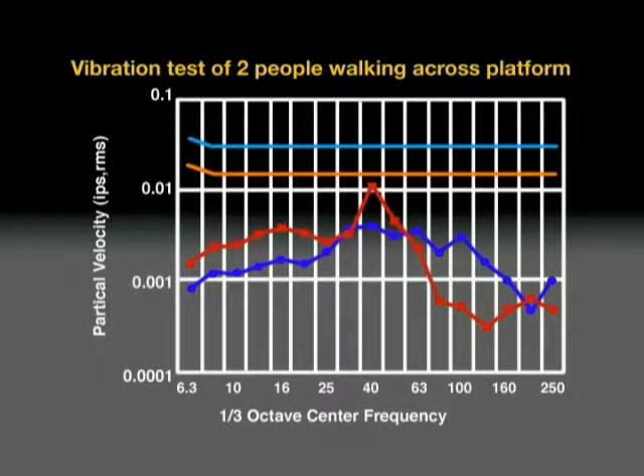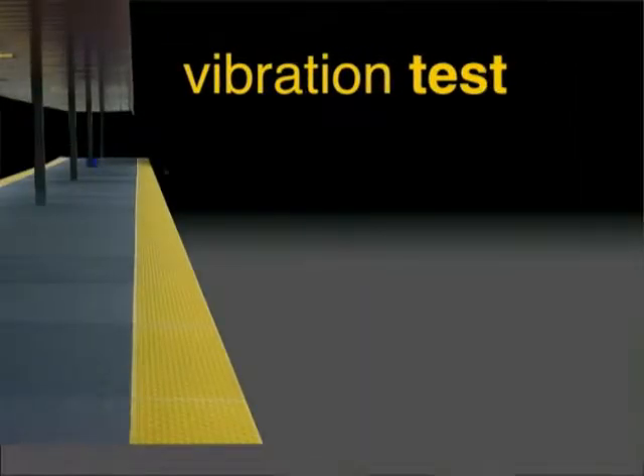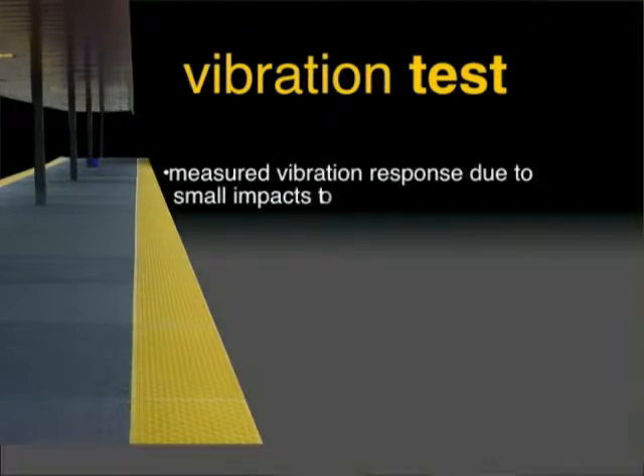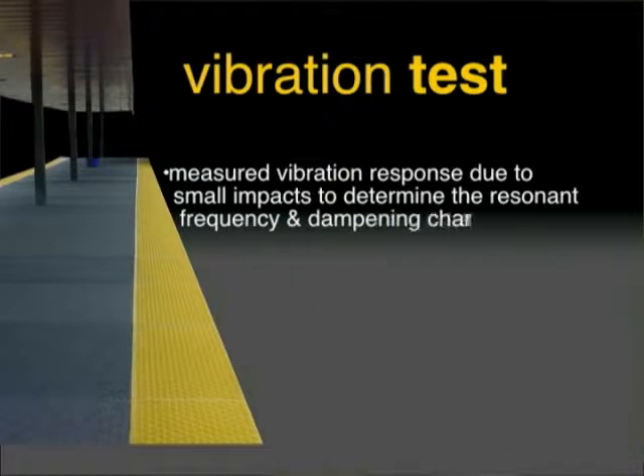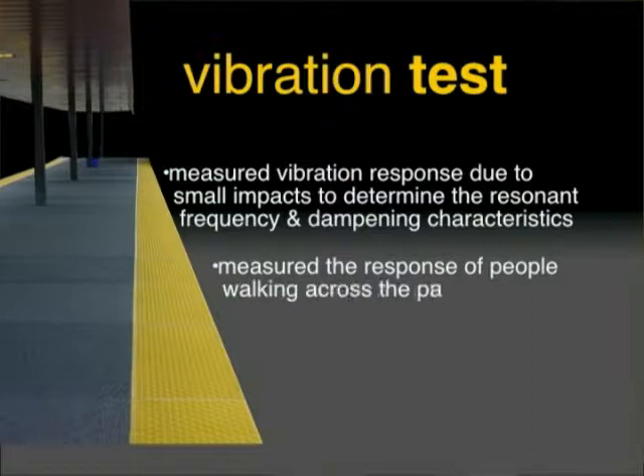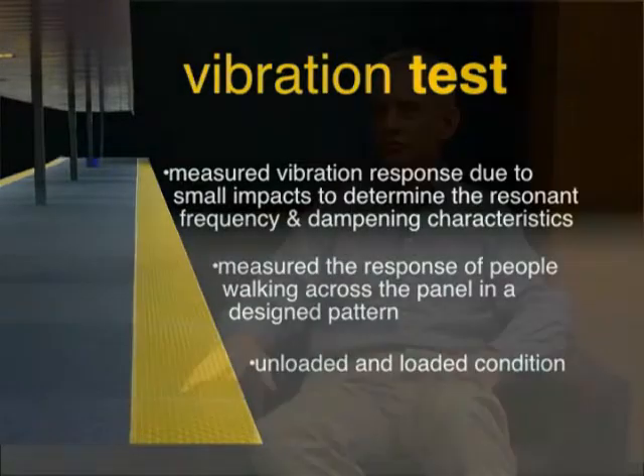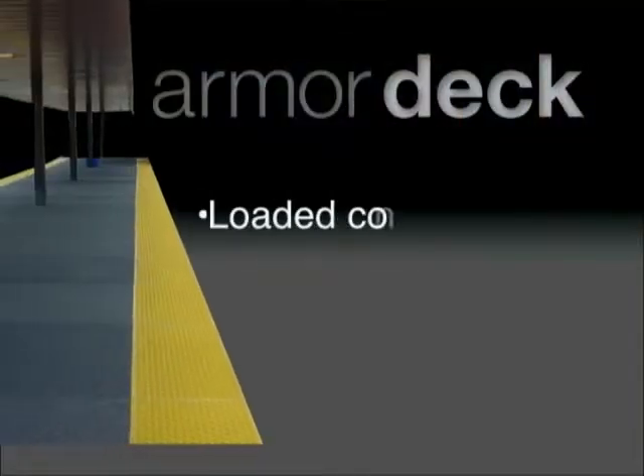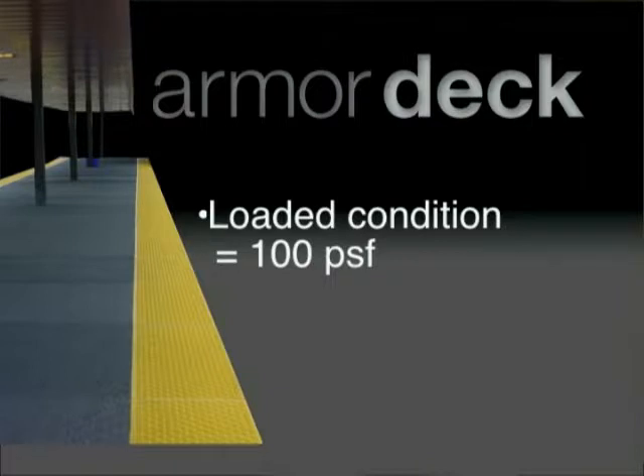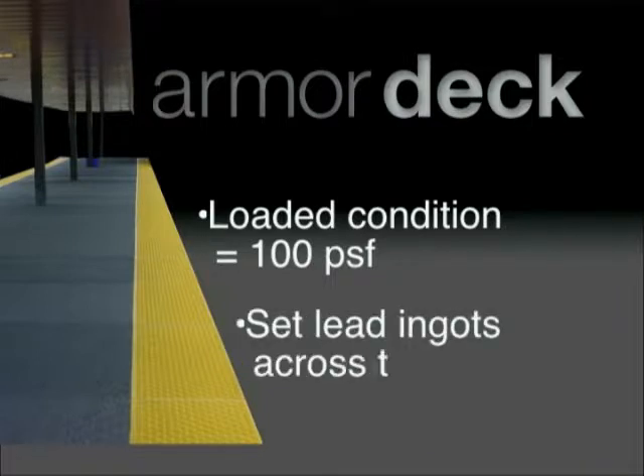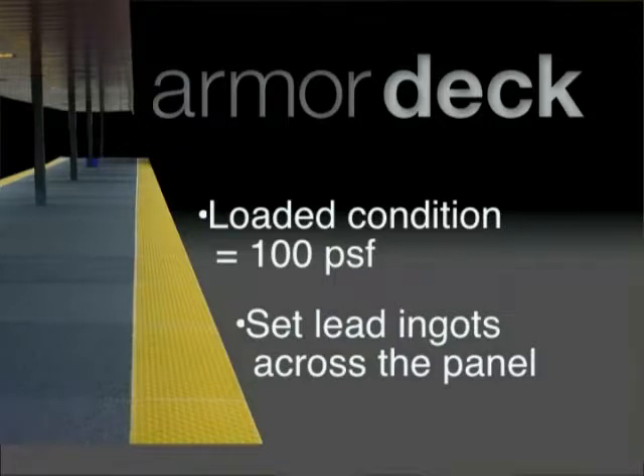And the testing that we did showed that the vibrations on these panels were no larger than walking on a similar concrete panel. We set up the panel in the lab, measured vibration response due to small impacts to determine the resonant frequency and the damping characteristics of the panel. Then we had people walk across the panel in a designed pattern and measured the response of people walking on the panel, both in an unloaded and a loaded condition, where the loaded condition was 100 PSF uniform load. We achieved that load by setting lead ingots across the panel surface, leaving a traffic pattern for the people to walk through, and we measured the dynamic response as they walked across the panels.